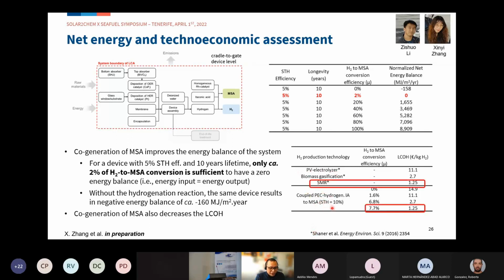This analysis shows that if you have a solar-to-hydrogen efficiency of 10%, and you can transform or at least use 8% of your hydrogen for this coupled hydrogenation concept, we can arrive at an LCOH of hydrogen that is very much competitive with hydrogen produced even with a fossil fuel-based approach. So this feasibility study provides motivation to pursue this approach.